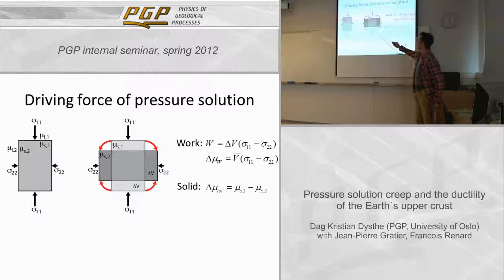The work equals the volume times the stress difference here. And this corresponds to the main driving force of pressure solution. The main difference in the work term is the most important driving force for pressure solution. It's just the partial molar volume times the difference in stress of the two faces.